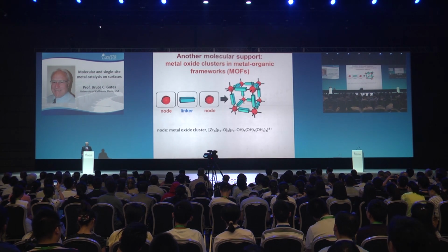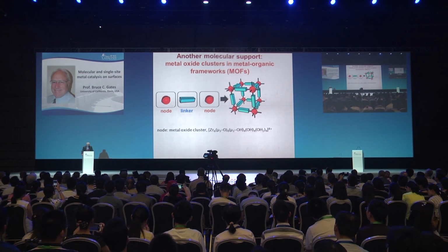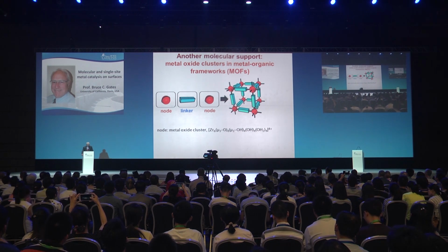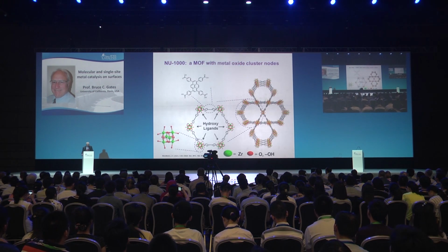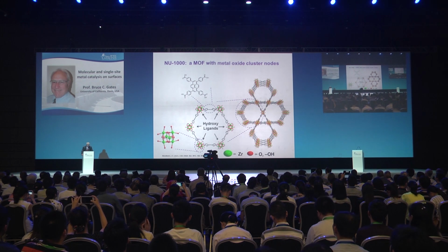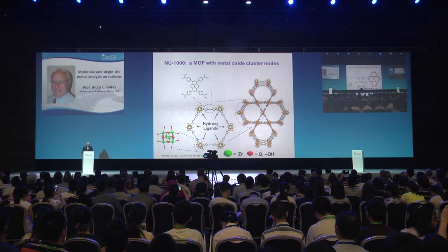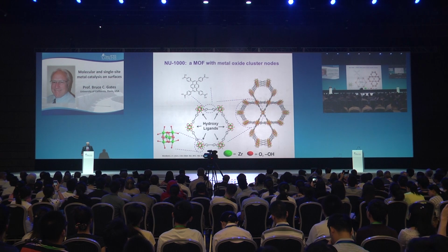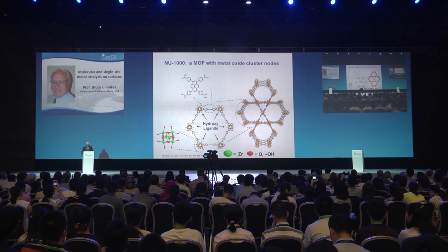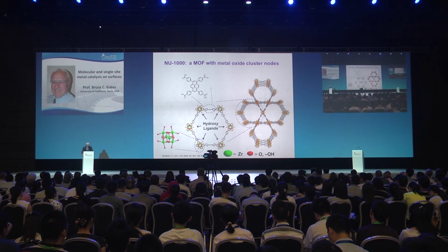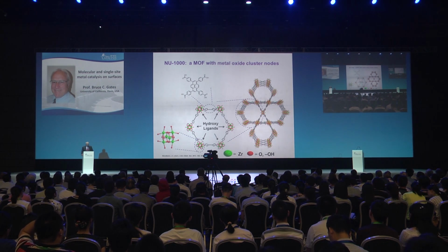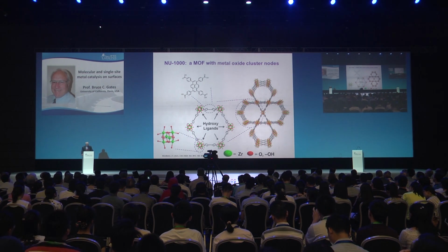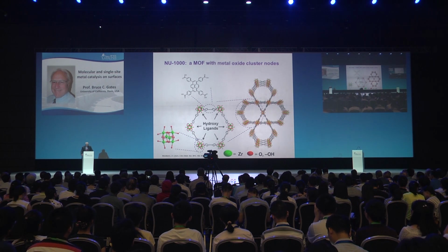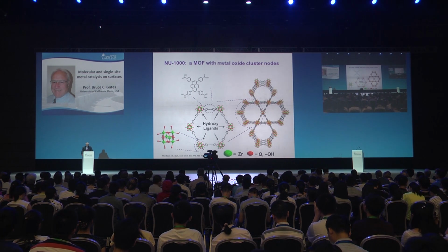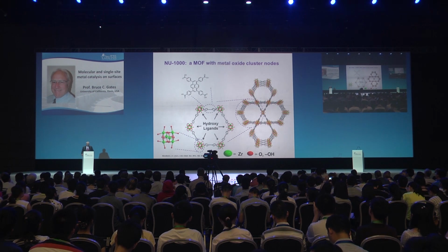Let's now talk about a different class of support, MOFs. They're combinations of linkers and nodes. We're going to talk about this particular MOF, which has pretty large pores, greater than 1 nanometer in the smallest case, and greater than 3 nanometers in some of the other pores, so well-accessible sites. The linkers are common ones in MOF chemistry. The supports are little pieces of metal oxide, 6 zirconium atoms per node.